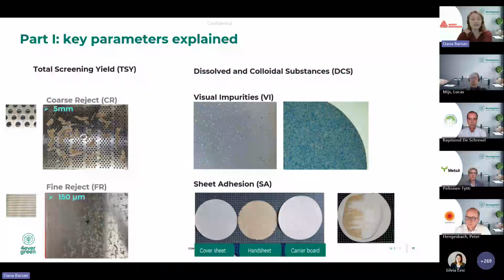If we go ahead and deep dive a little bit into these key 4 parameters, I can explain a bit better that the total screening yield is calculated based on the accumulation of the coarse rejects that have been separated in 2 screening processes, a coarse screening process with very large holes in the mesh. 5 millimeter particles are separated here. Particles like pieces of films, foils, metal clips, screws, plastic windows, tapes, and so on. These are the type of materials that come out in the coarse screening.